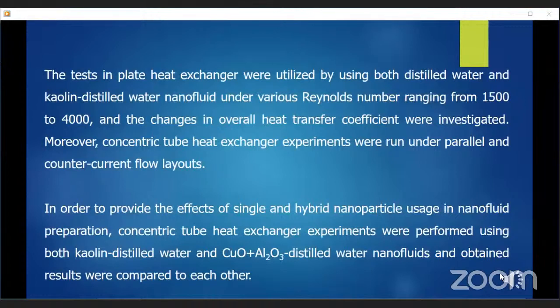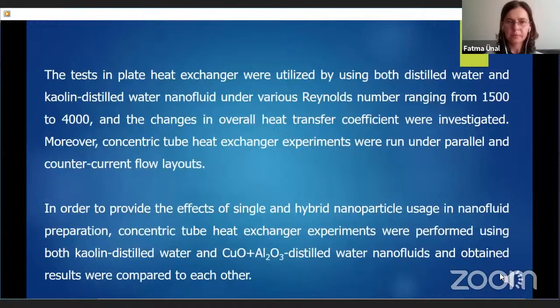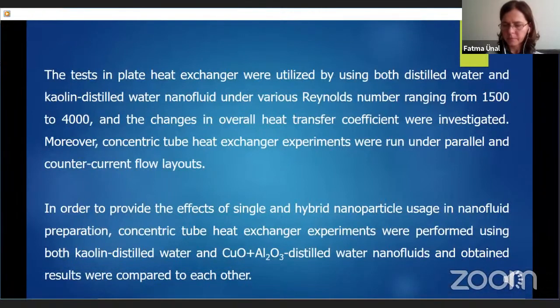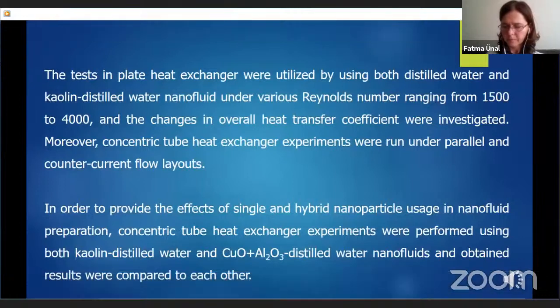The tests in the plate heat exchanger were carried out using both distilled water and kaolin distilled water nanofluid under varying Reynolds number, ranging from 1500 to 4000, and the changes in overall heat transfer coefficient were investigated. Furthermore, concentric tube heat exchanger experiments were run under parallel and countercurrent flow layouts. To show the effects of single and hybrid nanoparticle usage in the nanofluid preparation process, concentric tube heat exchanger experiments were performed using both kaolin distilled water and copper oxide alumina distilled water nanofluids, and the obtained findings were compared to each other.